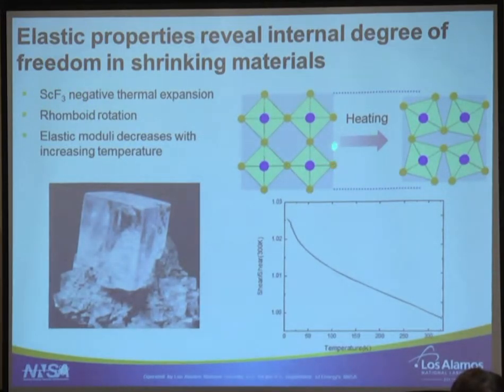So you have a rhomboid, and when you heat it, it shrinks, but because these things are rotating, you have another interatomic potential, and what you measure is actually a softening. You don't see something that is getting stiffer; you see softening like you would expect in a standard metal. And what it's telling you is that in reality you have some free parameter inside that you're not seeing. In this case, it is the rotation. This free parameter can be electronic, can be magnetic, can be anything. But just by measuring the elastic moduli as a function of temperature, it can tell us a lot.